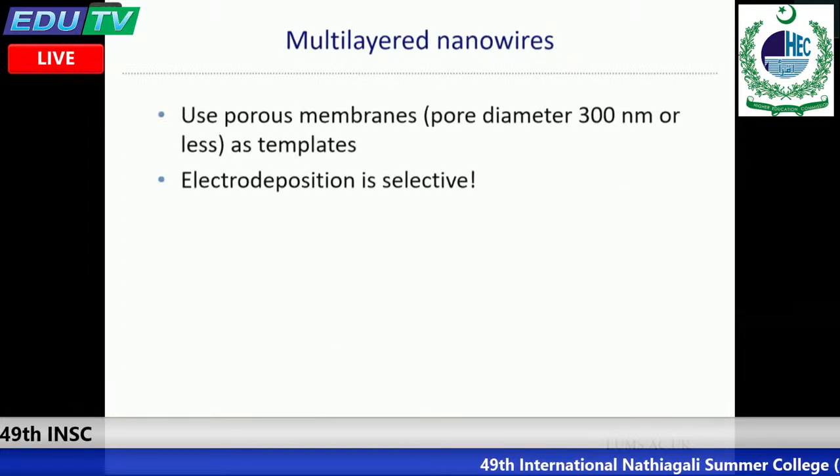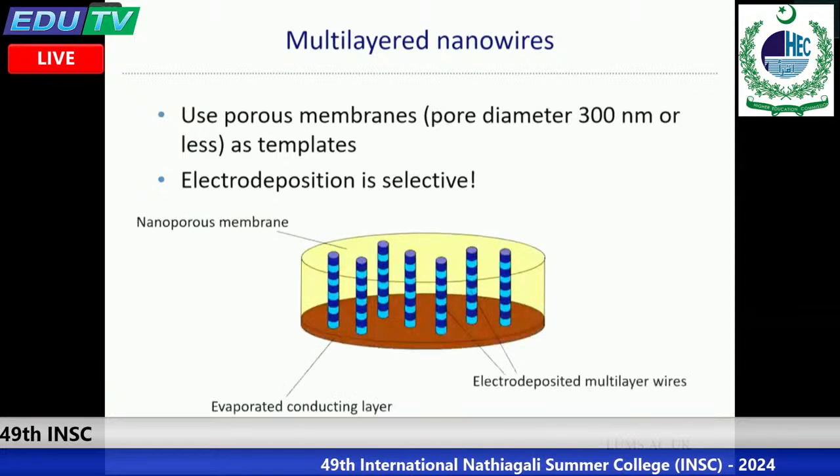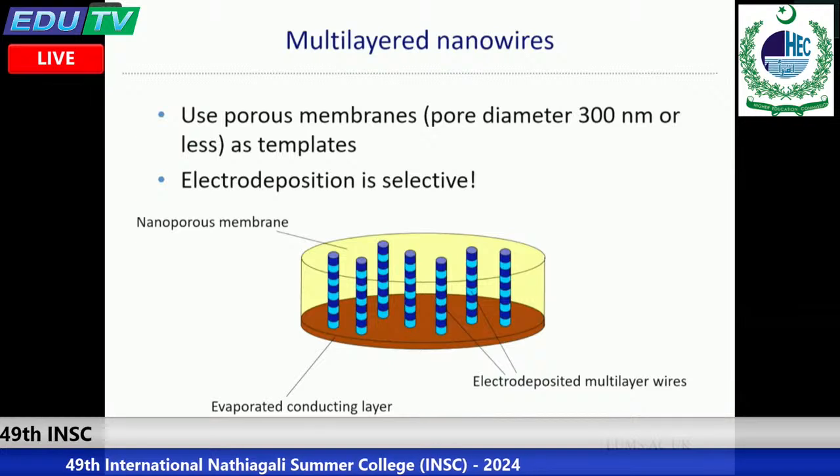And what I also would point out is that you can get materials which are nanostructured in all three dimensions by combining that process which I mentioned with deposition in a template. Template could be something like anodic aluminium oxide, or it could be a polycarbonate membrane in which holes have been etched as ion tracks. But however you have a nanoporous membrane, if you grow the multilayer in it, then you can get nanowires, the kind that we've been hearing about before. But what is different about these nanowires is that they are nanostructured also in the growth direction.